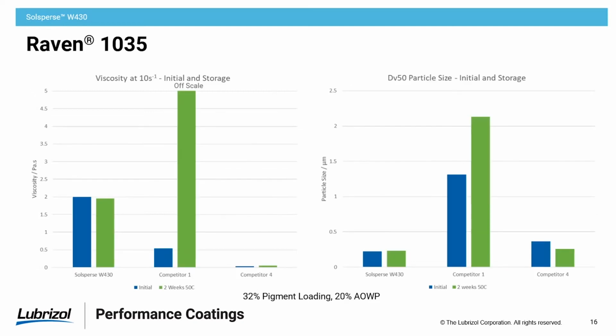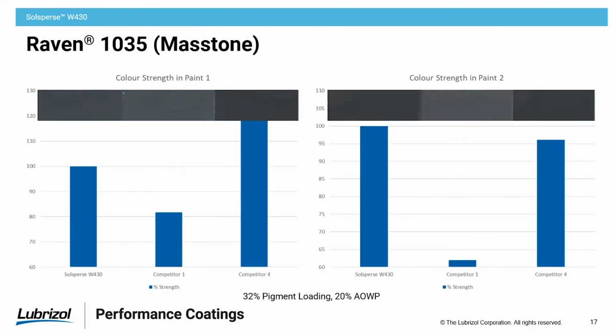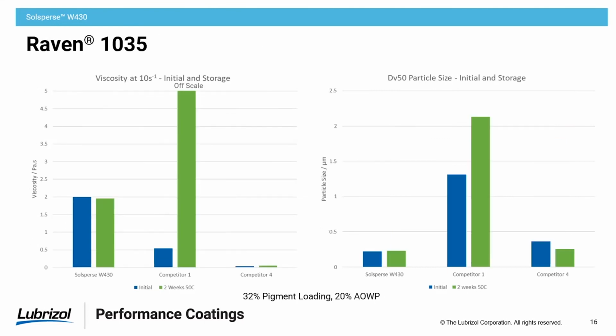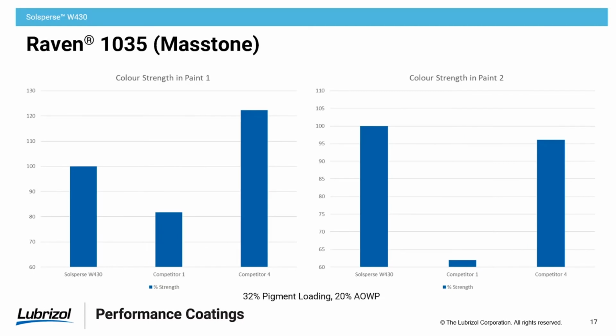For carbon black, we're looking at a variety of different carbon blacks. Here we're looking at the Raven 1035, which is a mid-color type pigment, can be used for mass tones or in tint. We have here nice viscosity stability, most important, not always the lowest particle size or lowest viscosity, but the best viscosity stability. And this is a big challenge when working in carbon black. In terms of the mass tone color, we're doing pretty good. If we look at competitor 4, that was a higher performing dispersant, and so it's a little bit better performance overall than the W430. But across the board, W430 is a competent performer for this system, the 1035 mass tone.